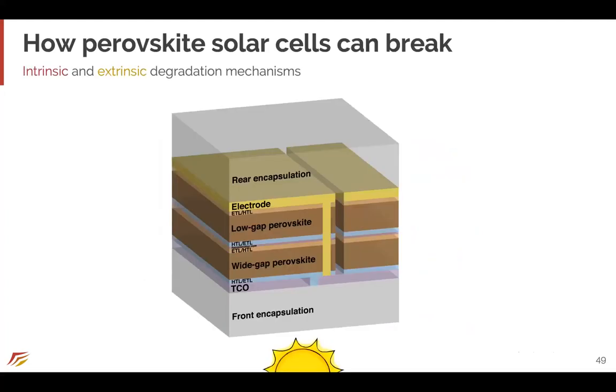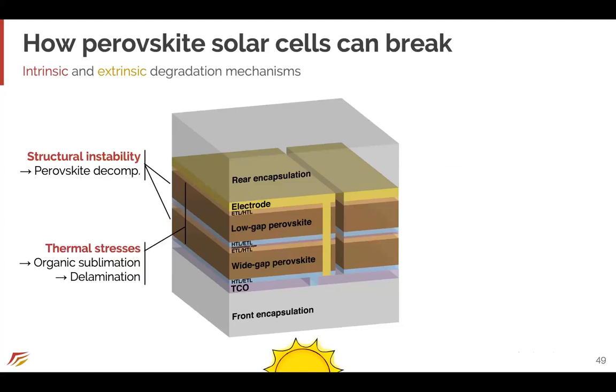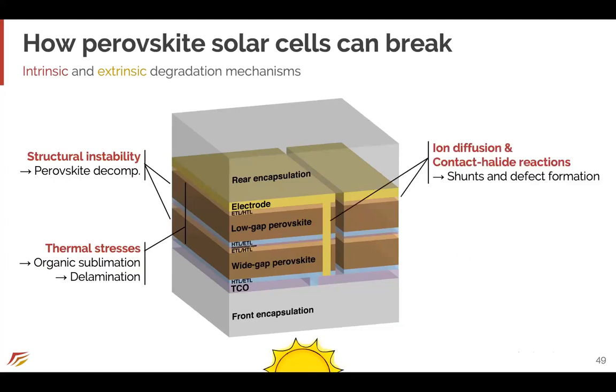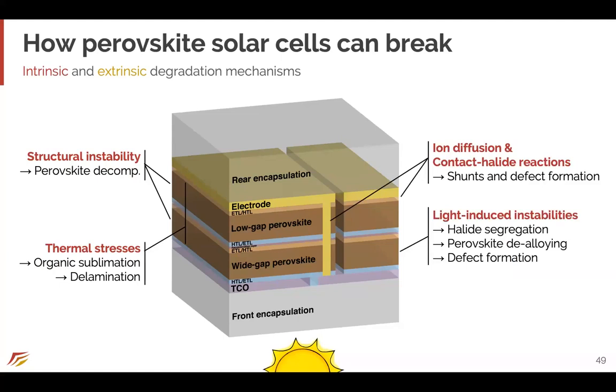So if we look at how perovskite solar cells might break, to try to understand that science, there's a lot of different mechanisms, intrinsic and extrinsic, that we need to understand and solve. So a lot of intrinsic ones, which happen even in inert conditions. There's structural instabilities in the perovskite, which can lead to decomposition. There's thermal stresses, which can cause the organic cations in the perovskites to leave, to sublimate, and also cause delamination between any of the layers in the stack. Ion diffusion can happen, leading to these contact and halide reactions, which tends to cause shunts and defects in the cell and reduce performance. We can also have light-induced instabilities, anything from halide segregation to dealloying of the perovskite to defect formation.